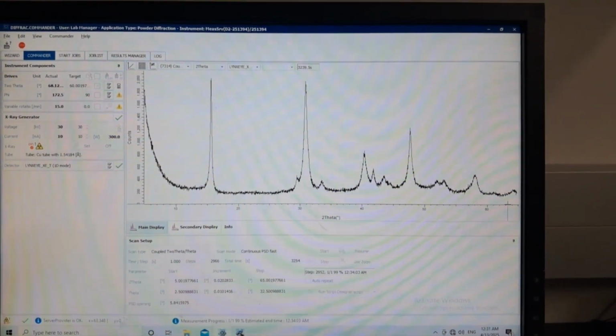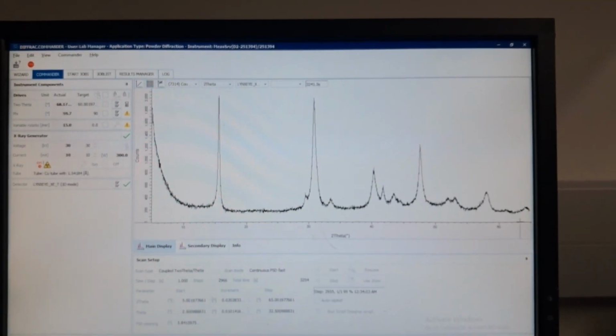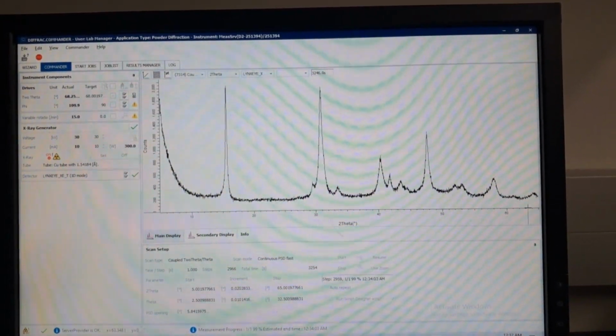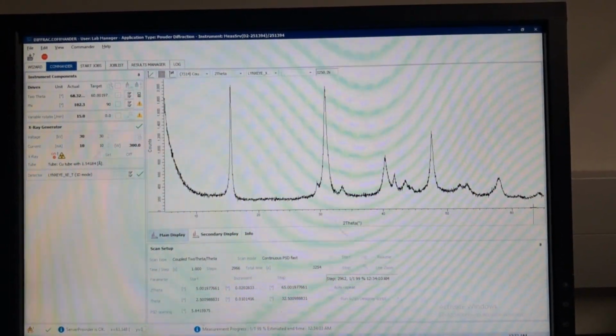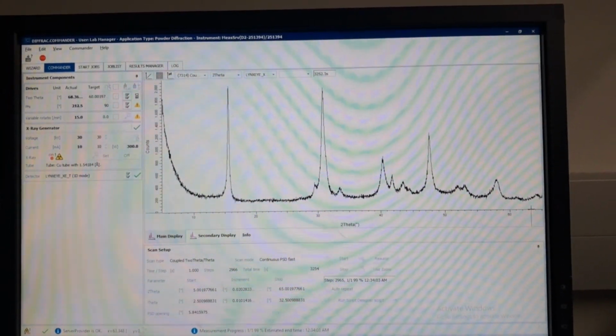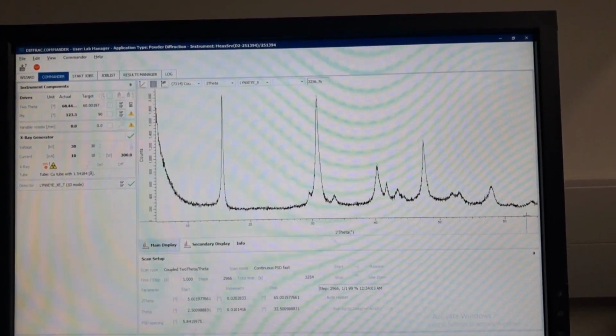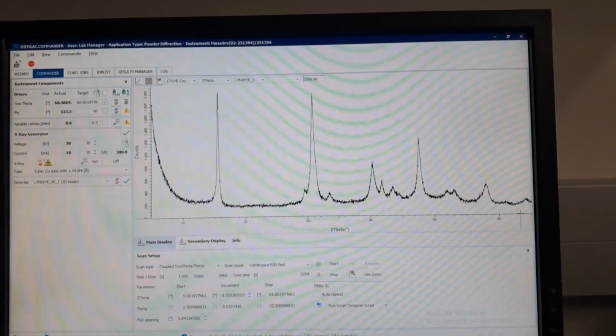We're just about at the end of that 1 hour run that had the ground samples. We see the same peaks that we saw before, but we also see other peaks of the unground samples emerge that had previously been dominated, with the preferred orientation effect being taken into account. Using this pattern, we should be able to perform Rietveld or Le Bail refinement.